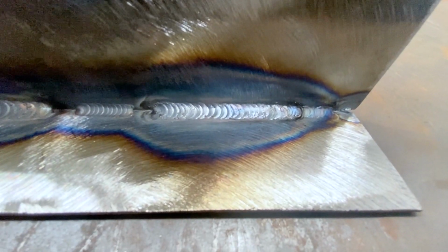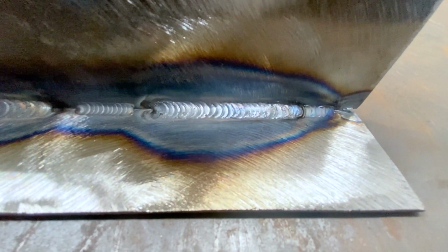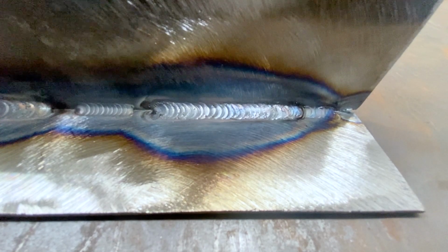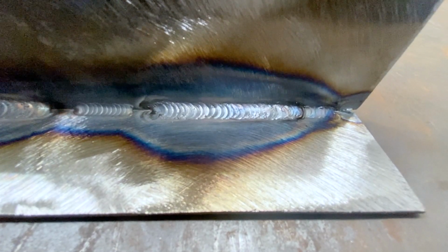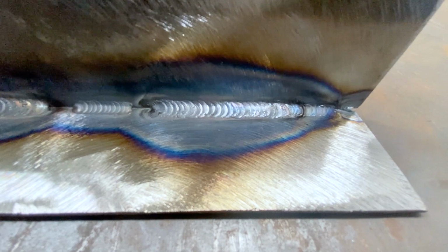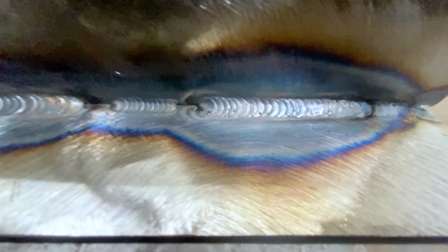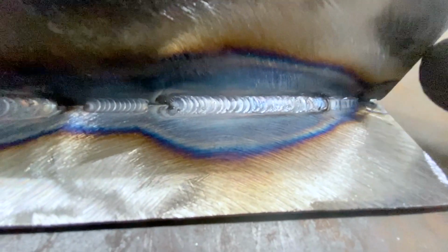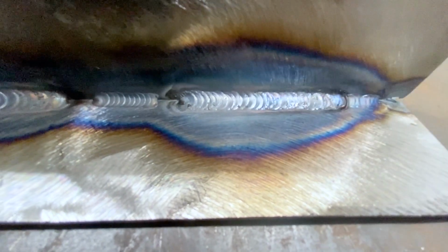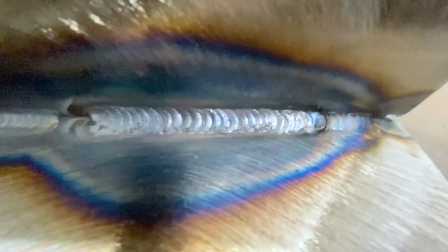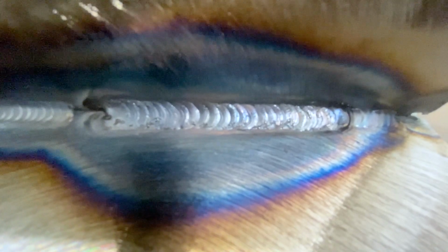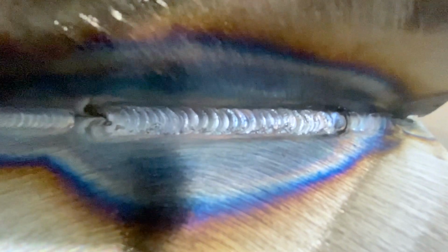Okay, so y'all just saw the arc shots of what was going on, showing how a puddle was too cold, too hot, ideal, and dirty material. Now I'm going to show you the results of that, what you were seeing. You can see here, I'm going to zoom in. This was the dirty material. You can see all the oxides and mill scale that's being pulled in. And you can see every bit of that in your puddle if you're paying attention. That's why it's important to keep your material clean at all times.